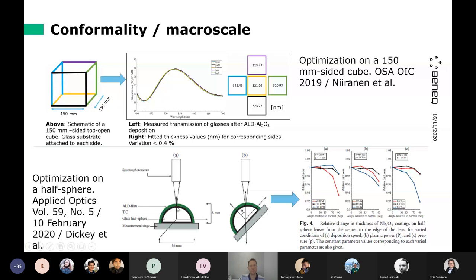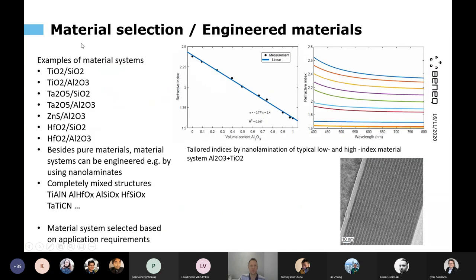Here another example where ALD is used to coat half spheres, and then a special test method was used to measure the film thickness on the half sphere at different angles. And in this paper there were studies made on process condition optimization to get very uniform film throughout the whole structure. Okay, so ALD can make conformal films.